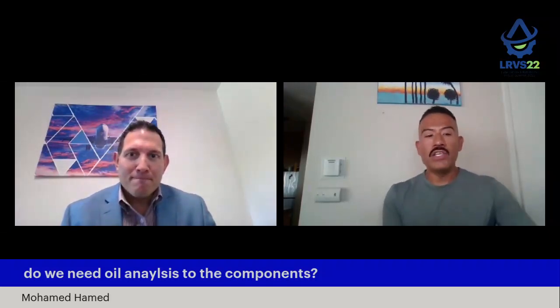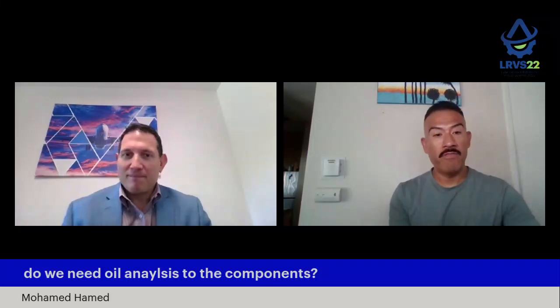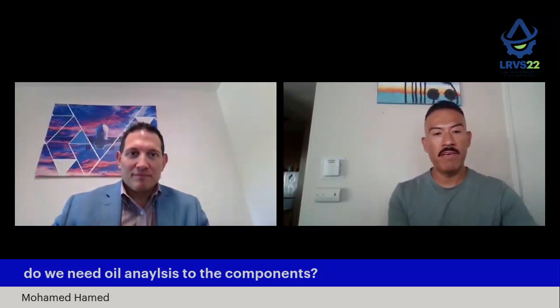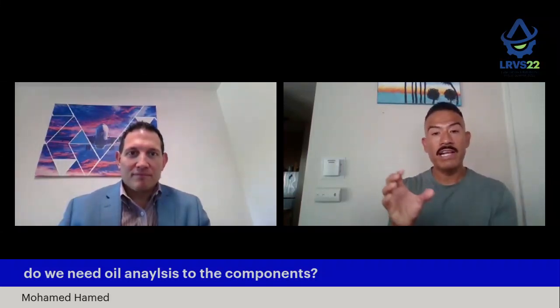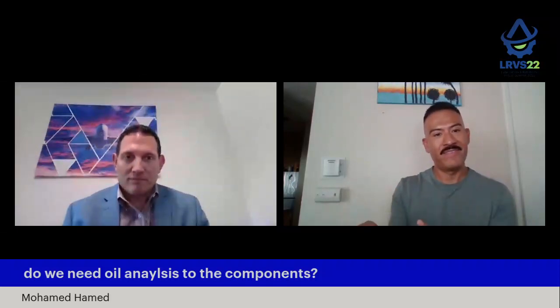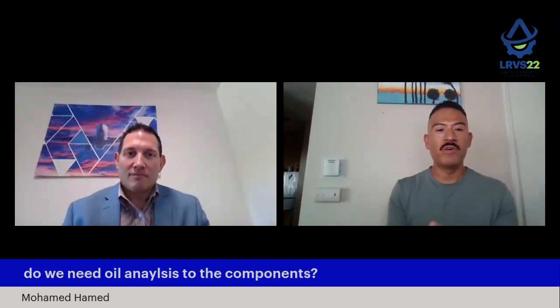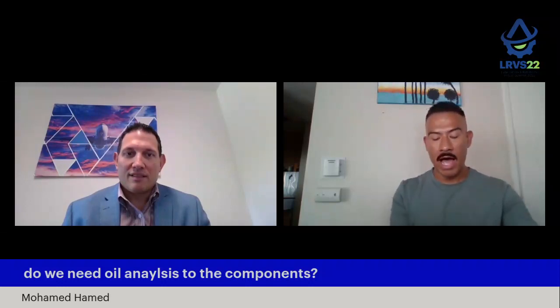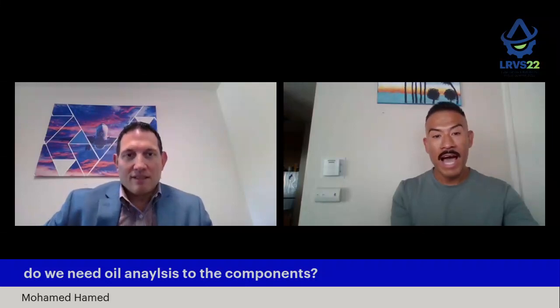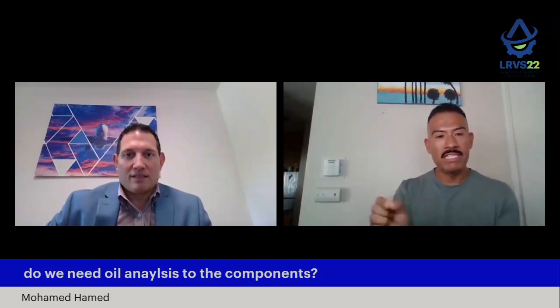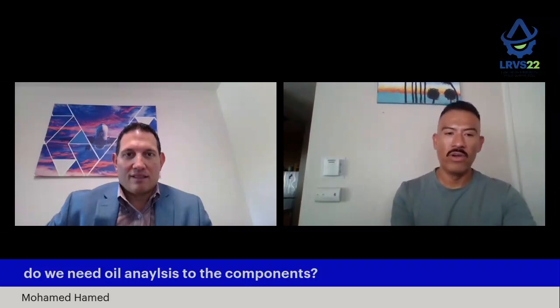Yes, we do. Something that we notice, especially for some of the fancy lubricants, like the MACs or the PFPEs, is that they sometimes chemically react with some stainless steels, and they produce what we call the Lewis acid attack. So every time we try a different grease with a different additive, we have to test for compatibility with the base material, and it's normally performed by a chemical analysis of the oil.